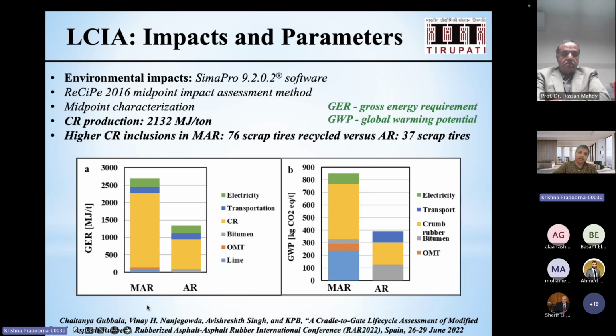So if you look at this here, modified asphalt rubber versus the asphalt rubber, obviously the GWP was higher, as you see here, except for the fact that crumb rubber by itself takes up a lot of energy in terms of shredding. So let's assume the government is giving you a subsidized rate. Then you basically see that MAR functions much better than the AR, as mentioned in this case.